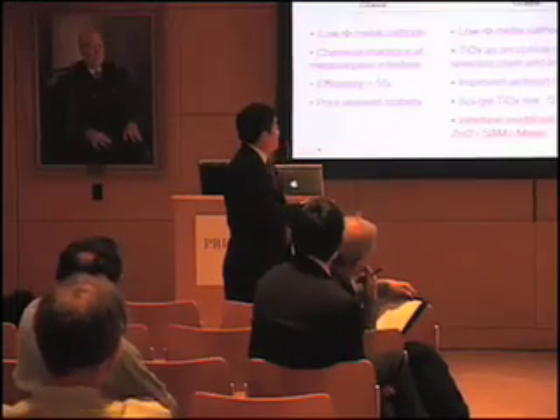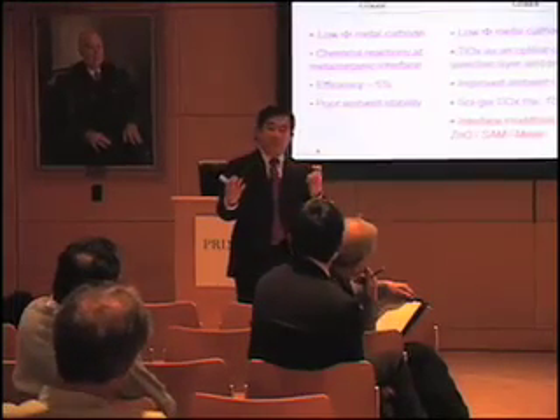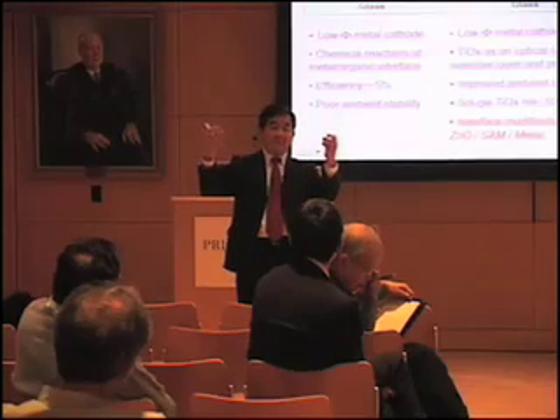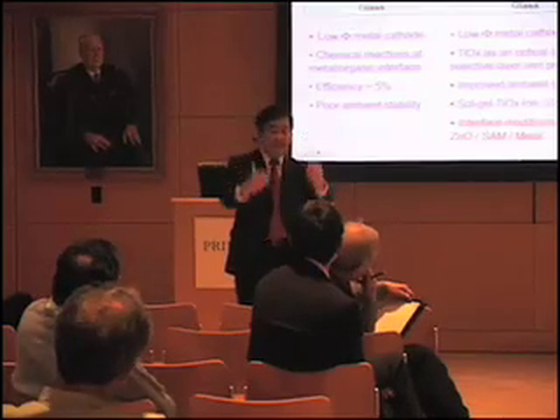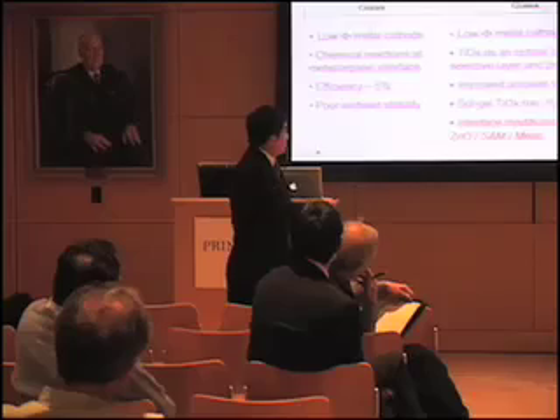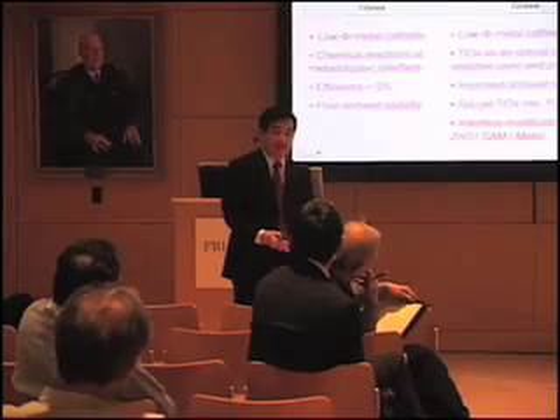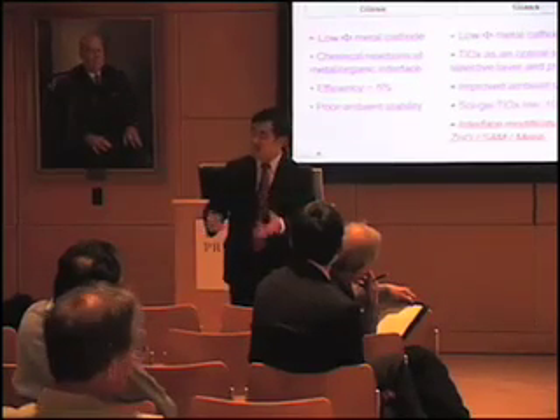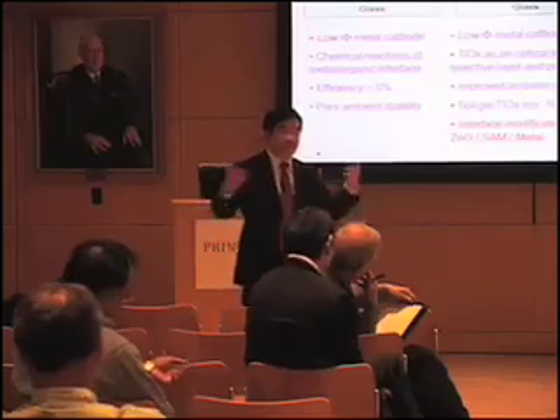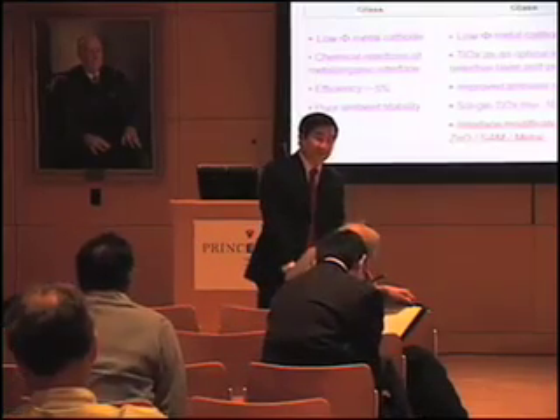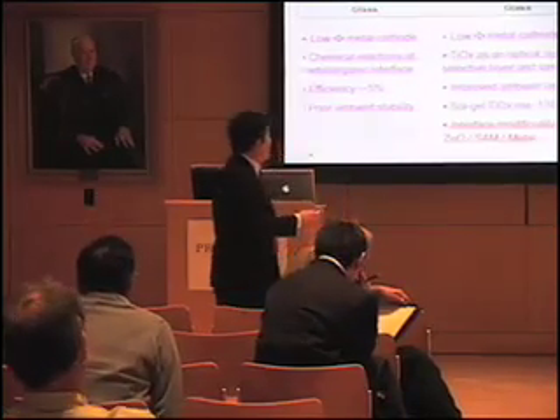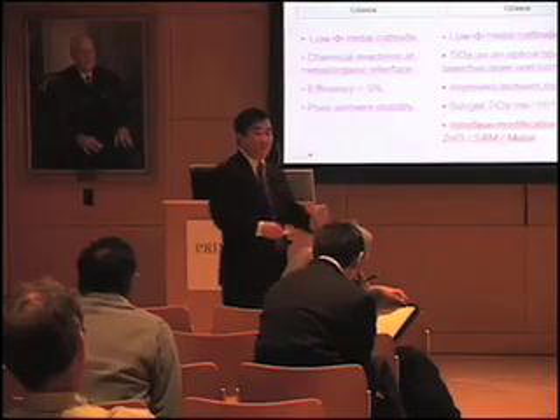But now you have polymer blends. When you have polymer blends, you have P-type material, you also have N-type material, right? So if both of those materials touch the surface, sometimes the charge selection is a problem. Both charges can try to leak through your device. So if I have a C60 in here, right? C60